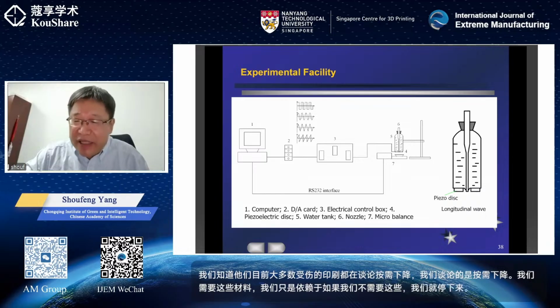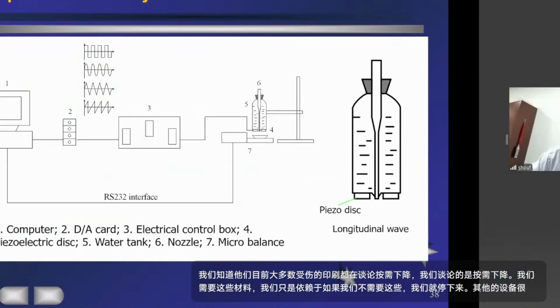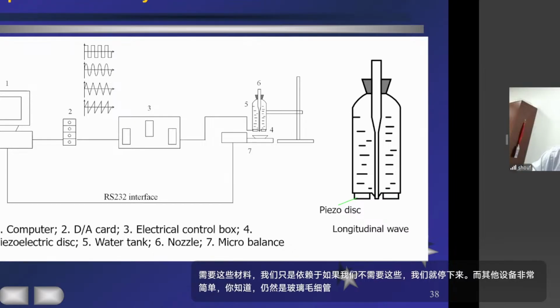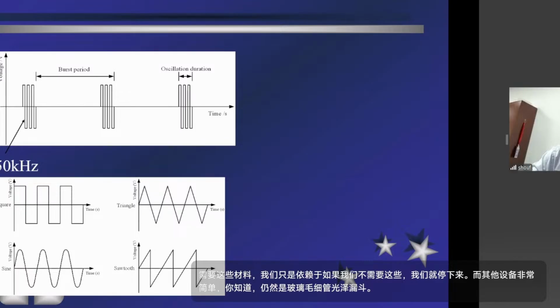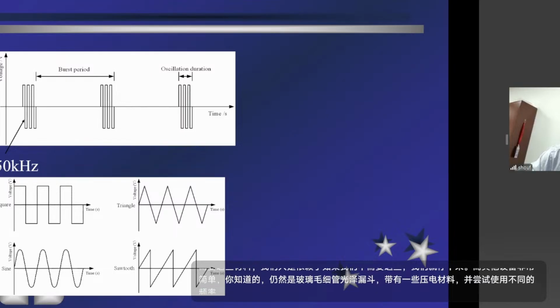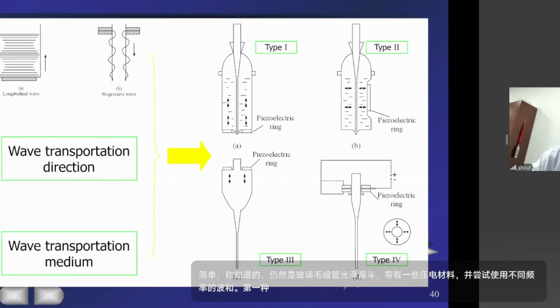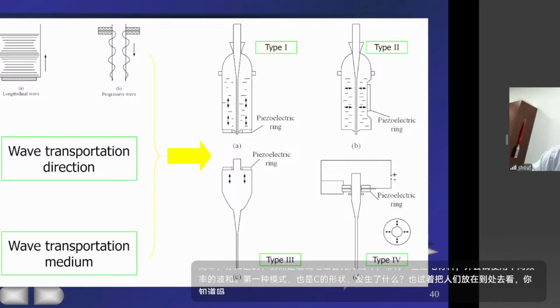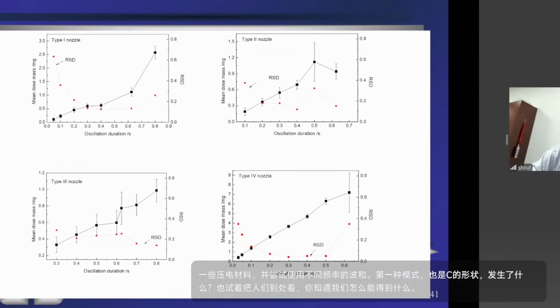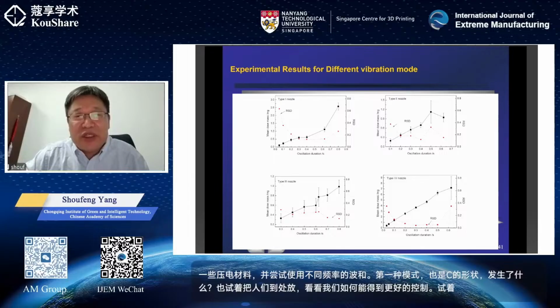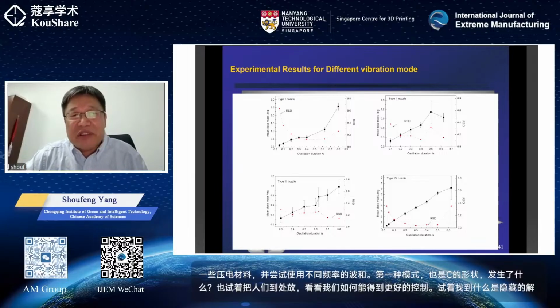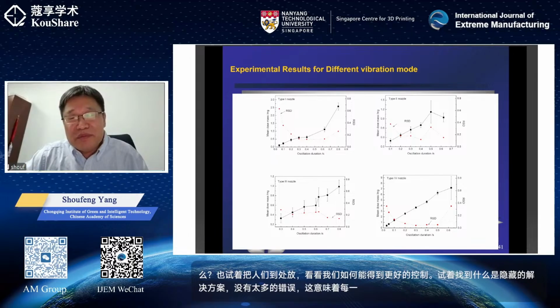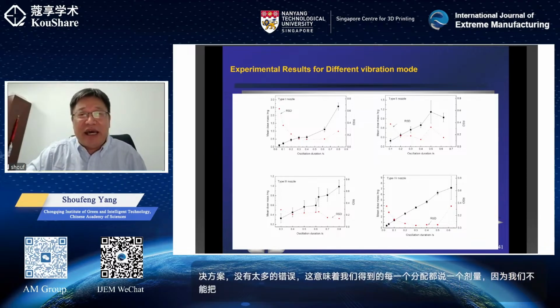And the device is very simple, still the glass capillary, glass hopper with some piezo, and we try to use different frequencies of the wave and burst mode, and also shape, to see what happens. We also try to put the piezo everywhere to see how we can get better control, and try to find the highest resolution without much error. That means every dispensing we get the same dosage, because we can't put a balance inside a printer, right?